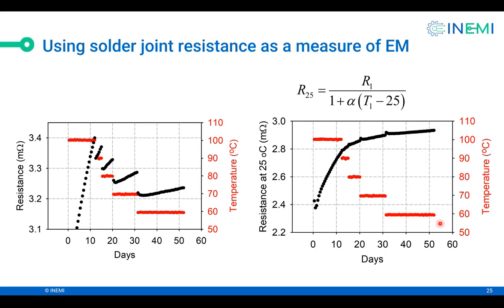So here is how we do the experiment. Okay, so we take a specimen. In this case, I'm showing you just one solder joint. And on the vertical axis is the resistance the data logger measures. And the resistance is in milliohms. The horizontal axis is the duration of the test. So this test ran from 0 to 50 or 60 days.